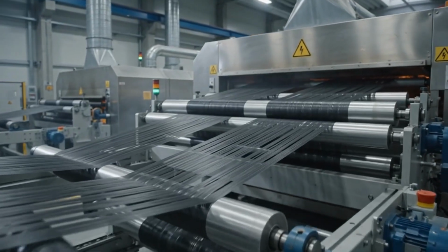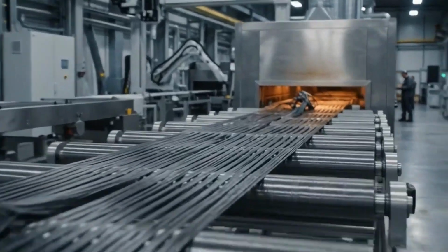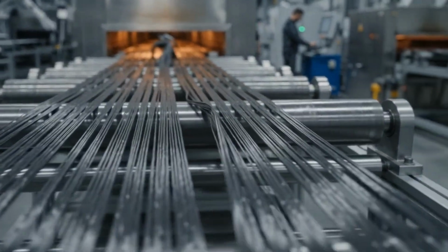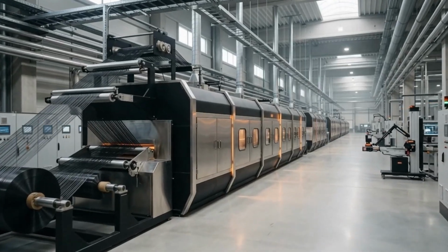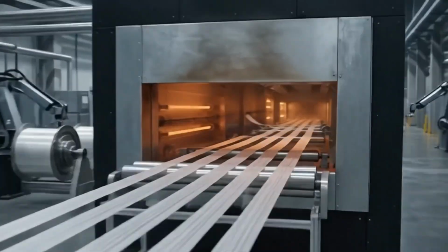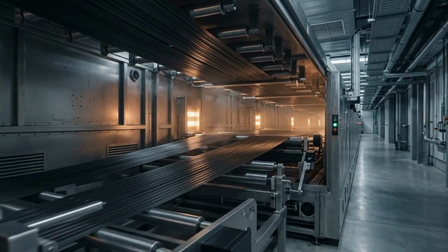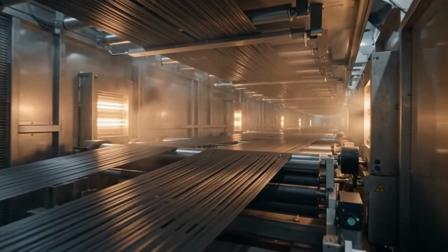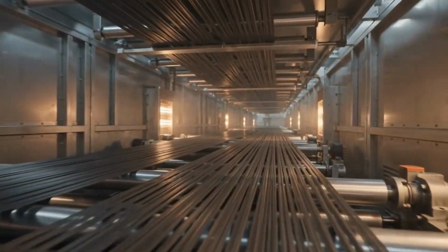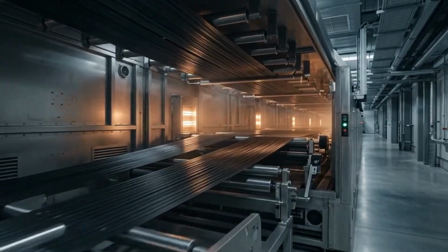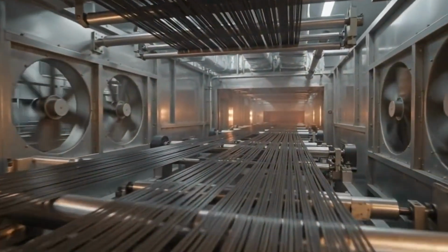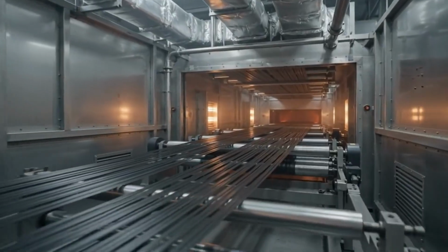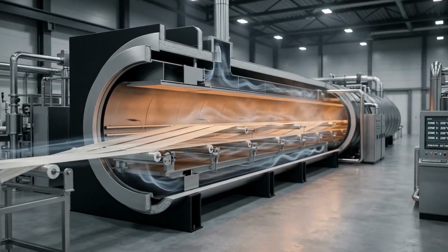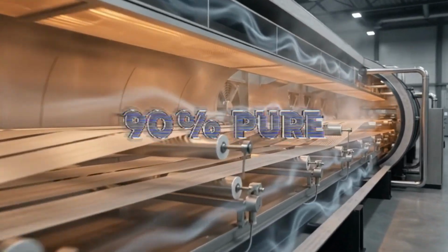After oxidation, the stabilized fibers move into the carbonization furnace, and this is where things get genuinely extreme. The fibers get heated in an oxygen-free atmosphere, typically nitrogen gas, at temperatures ranging from around 1000 to 1500 degrees Celsius. Why no oxygen? Because at these temperatures, oxygen would simply incinerate the fibers instantly. The nitrogen environment allows the heat to do its work without burning everything to ash. What happens inside that furnace is a molecular revolution. The heat drives off virtually everything that isn't carbon. Hydrogen, nitrogen, oxygen, and other elements get expelled as gases. What's left behind is a fiber that's now more than 90% pure carbon.